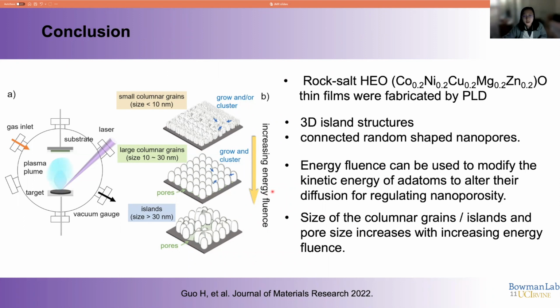Conclusions. In this work, we produced rock salt HEO thin films using pulsed laser deposition. And these films were deposited at a low temperature, 300 degrees, but still with a single phase structure and good crystallinity. Also, the film structure showed 3D island structures with connected random-shaped nanopores. So we also analyzed the energy fluence effect on the morphology and structure of the thin film.